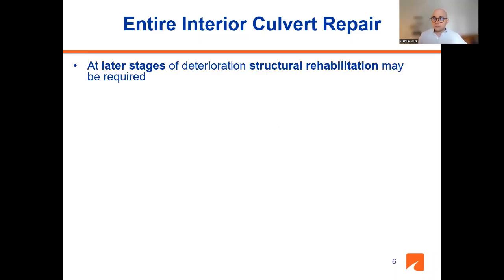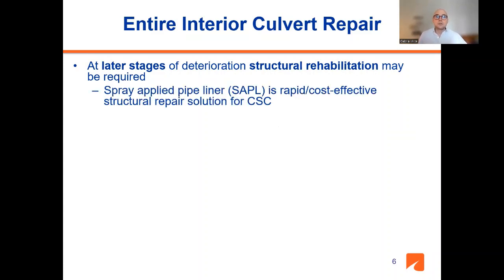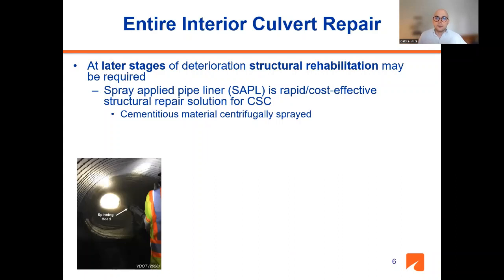Now, whenever we have more than just a minor invert deterioration, but a more significant deterioration that actually requires structural repair, one interesting option for structural rehabilitation is the use of spray-applied pipe liners. These are rapid and cost-effective solutions in which you basically use a cementitious mortar. This is usually fiber reinforced and is centrifugally sprayed.